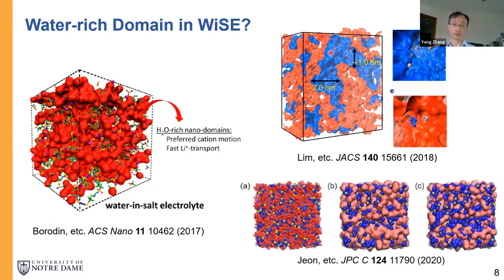However, 2 years later, the same South Korean group published another simulation work using a refined, supposedly better force field. In this simulation, they don't see any water-rich domain or water channel anymore. It's more or less a homogeneous system. So it's still puzzling till now, what's the liquid structure and why lithium can move so fast in this liquid phase. So we would like to use the techniques we have and try to see if we can provide an answer. So this is a simulation setup.